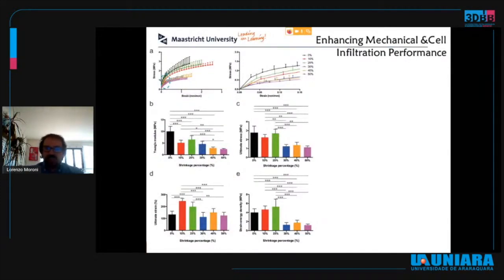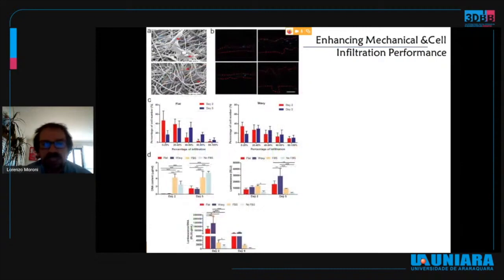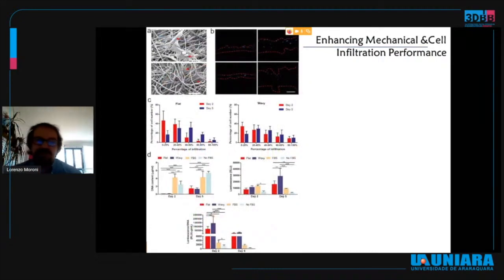The buckled scaffolds actually did their job. Not only did they have a modulation in the mechanical properties, but also, and more importantly, they resulted in the migration and population of cells through more than 1 centimeter in thickness of these constructs. But interestingly, what we also found was that the waviness of these structures resulted in the selective expression of TGF-beta, which is a growth factor common in tissue morphogenesis and especially connective tissue regeneration. So we are now also testing these waved scaffolds in a ligament model to see if the waviness pattern could also influence the regeneration of connective tissue such as tendons and ligaments.